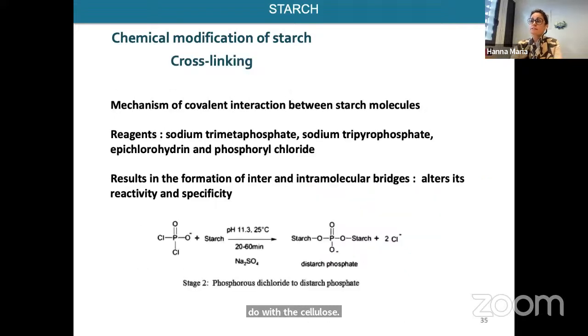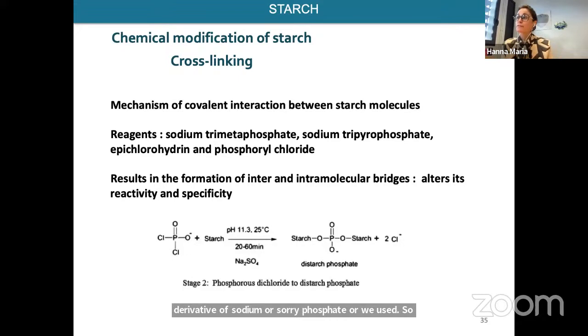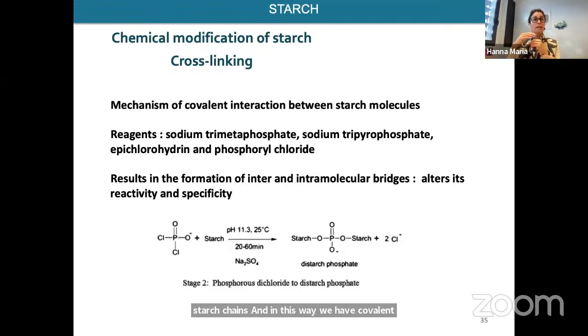Yeah, so for instance, I have an example about cross-linking. Here it's a mechanism of covalent interaction between starch molecules. To do it, we used a derivative of a phosphate, or sodium trimetaphosphate, or other kinds of phosphate you can use. And here it was to replace the hydrogen bonds between the starch chains. In this way, we have covalent chains, and we can improve the resistance of starch. And this kind of modification is used for starch derivatives that are used in food applications.